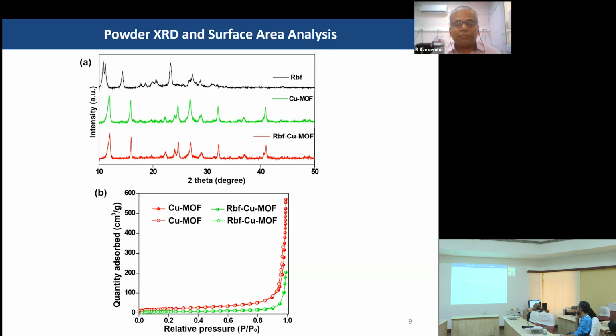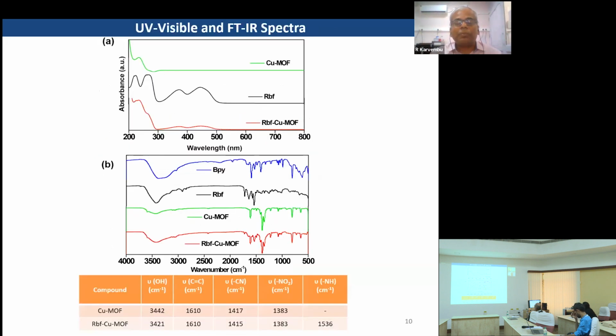We have measured the BET surface area, and the BET surface area of the pristine copper MOF is 79 meter square per gram, and that of the riboflavin MOF is 40 meter square per gram. So there is a considerable reduction in the BET surface area, indicating that the guest molecules, that is the riboflavin, occupied the surfaces of the pristine copper MOF.